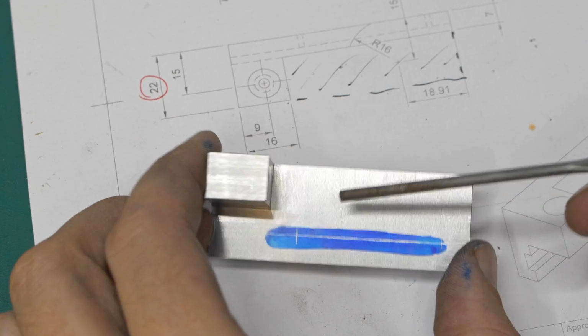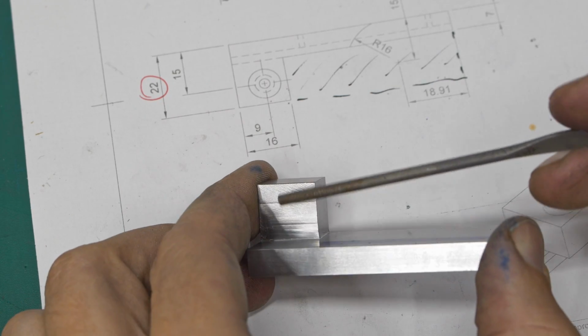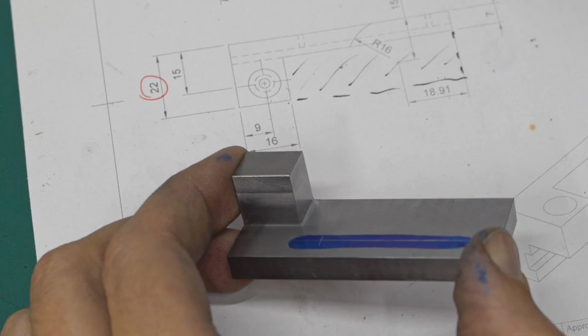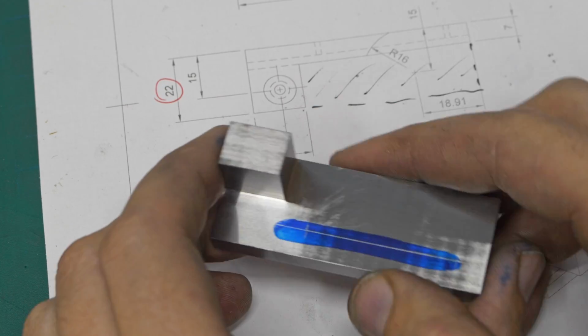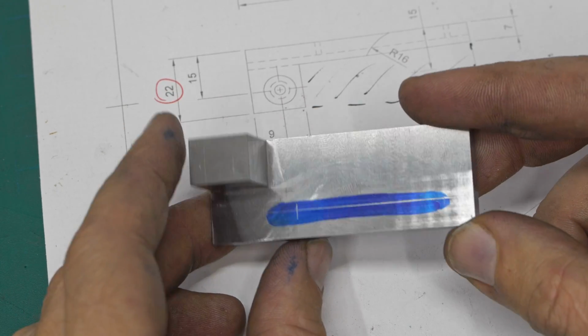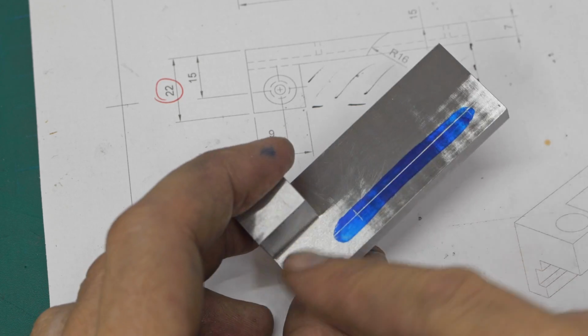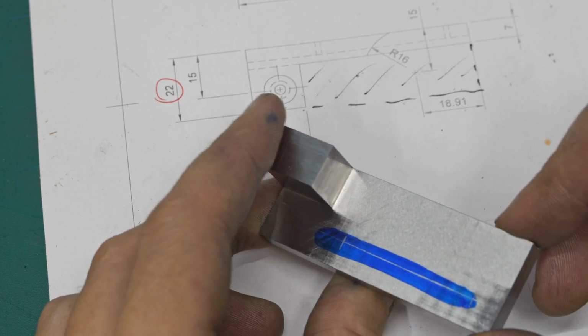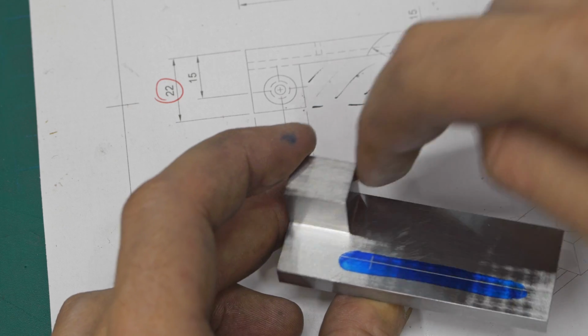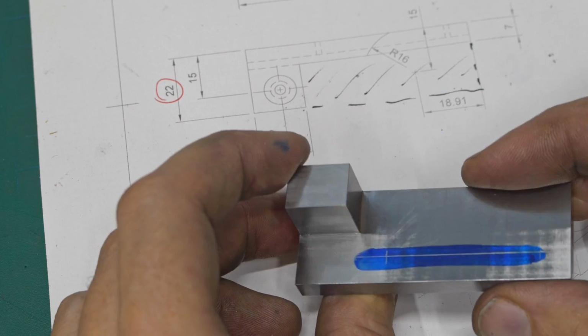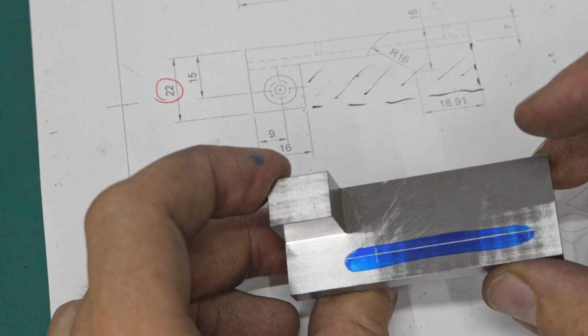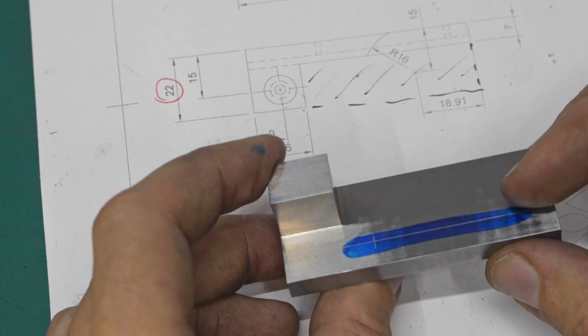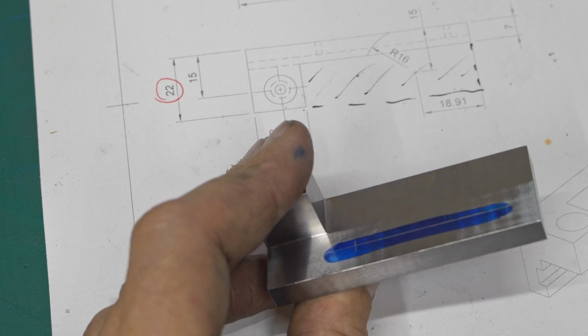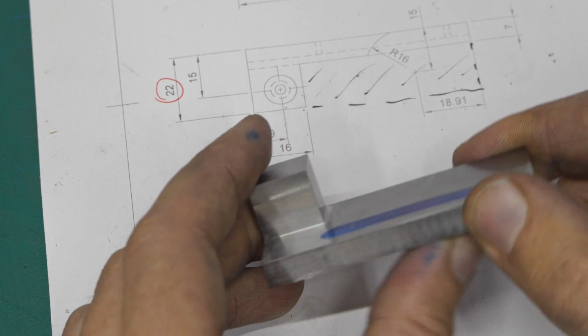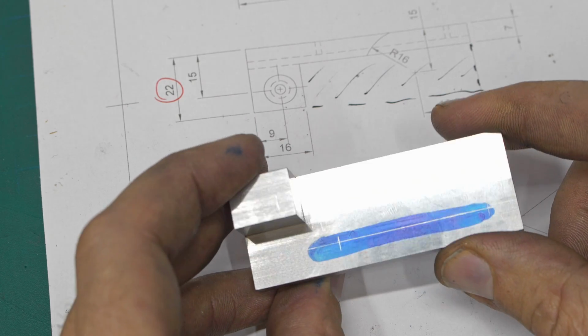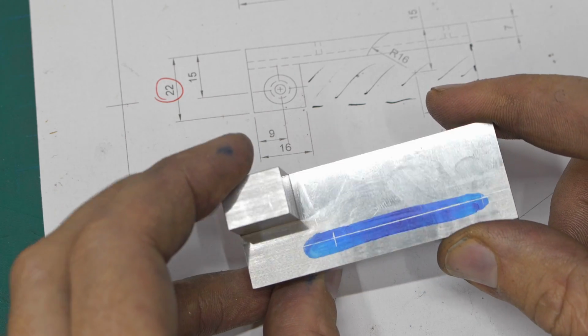You saw me milling this flat and also the 2 vertical walls of this post. And after milling, I took it over to a surface grinder and I just cleaned up in this direction, then swung it around 90 degrees and cleaned up this way too, and tried to blend it half decently. Walked away a little bit over here. There is a little bit of warpage in the part, but truth be told, I'm not going to bother with it. It's in the 5 micron region.